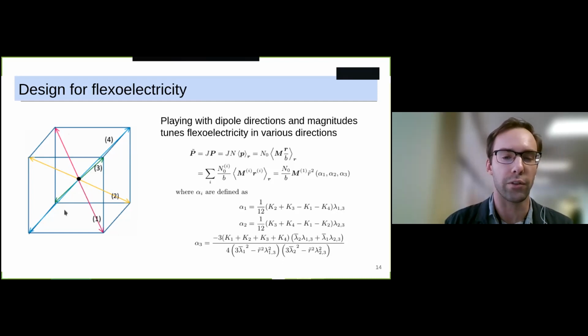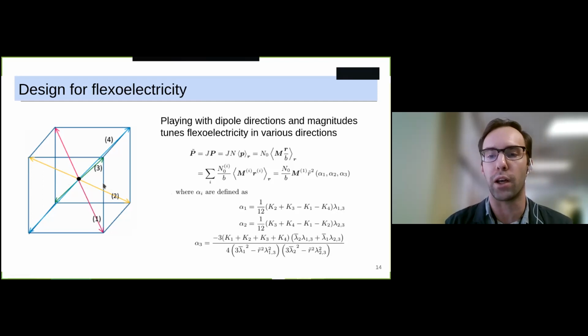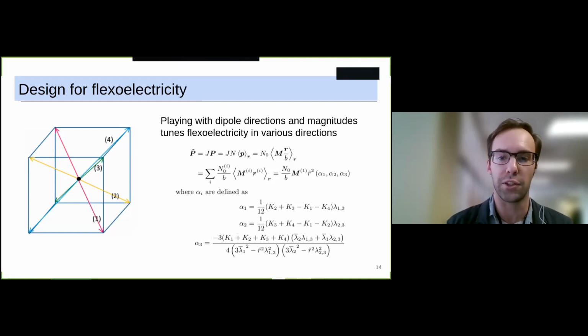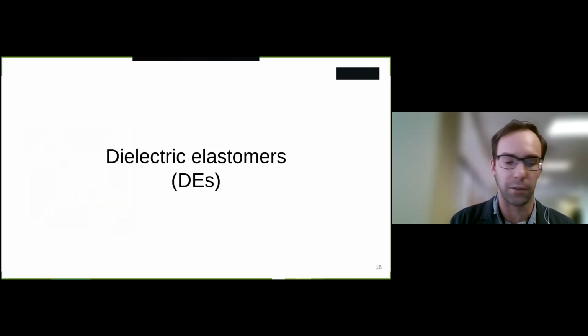Here there's really only one restriction, and that is we're applying this inversion symmetry. So the blue chains have the same dipole direction, the red chains have the same dipole direction. And this just leads to a material with a vanishing net polarization in the reference configuration, in the interest of material stability. But anyway, what you find when you do this is that you can now think about tuning the direction of the induced polarization with respect to the strain gradient in various directions, and enhance the flexoelectric effect in different ways. So this was quite interesting as well.